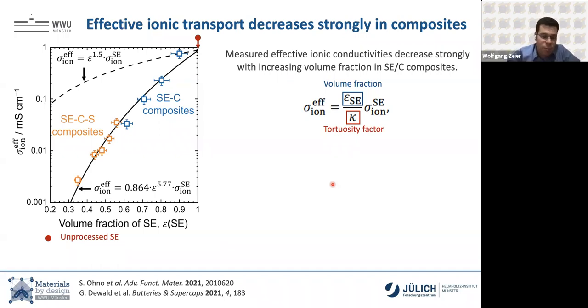This is a complicated plot, and I'll walk you through it. This is the measured ionic conductivity, our effective ionic conductivity, so the ionic conductivity that we have in the composite as a function of the volume fraction. This effective ionic conductivity is a function of the volume fraction, the tortuosity factor, so how tortuous a pathway is through a composite, and the ionic conductivity of your pretty much untouched electrolyte, so 100% solid electrolyte.